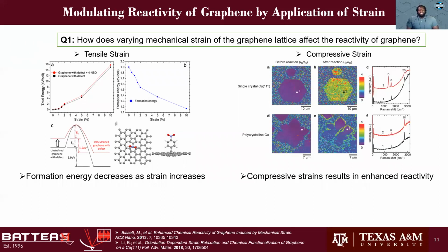And in this next work, the researchers looked at the chemical reaction of strained graphene islands on different copper 111 foils. They showed that single crystal copper induces more compressive strain in graphene due to lattice mismatch. And it's seen that this increase in strain has led to an increase in reactivity, indicated by the intensity of the D peak from the Raman spectroscopy, in comparison to the non-existent D peak shown with graphene transferred onto polycrystalline copper. But also it should be noted that the metal introduces electron density to graphene, and this electronic effect may affect the reactivity of graphene as well, and not just the compressive strain.